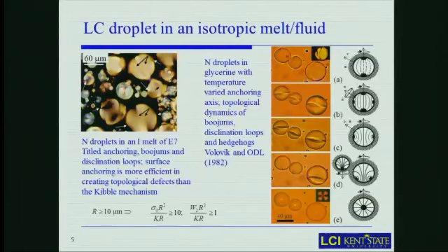And those are simple examples, so you can buy, if you are working for an academic institution, you can buy the liquid crystal. It turns out you cannot buy it when you are working from home. So you can buy this commercially available mixture and melt it and try to catch the temperature really close to the phase transition. And then if you're lucky, you would observe the droplets, big droplets of the nematic floating in the isotropic melt. This isotropic melt looks like black under a polarizing microscope with two crossed polarizers.